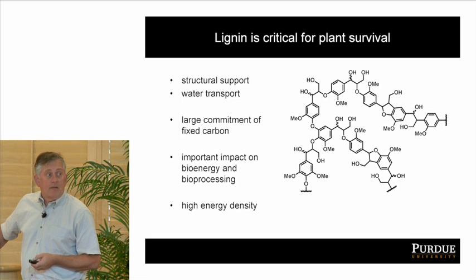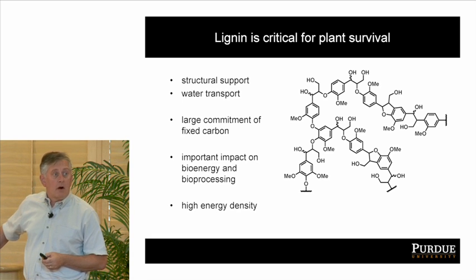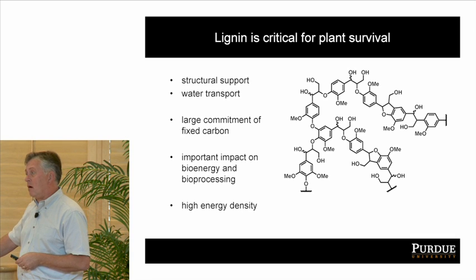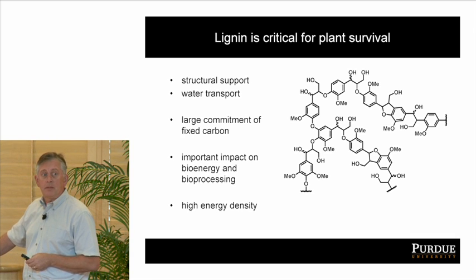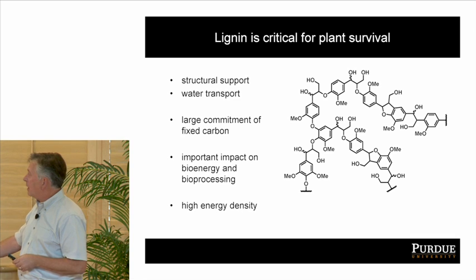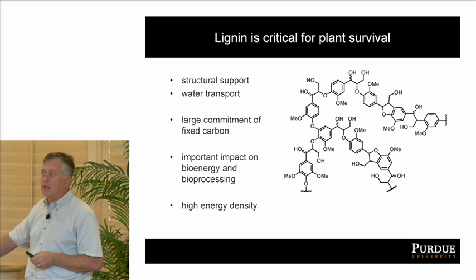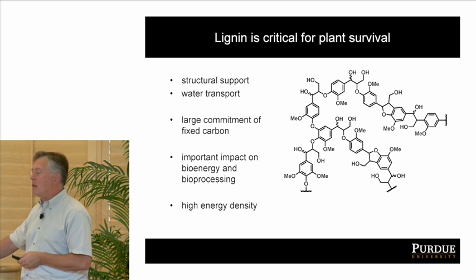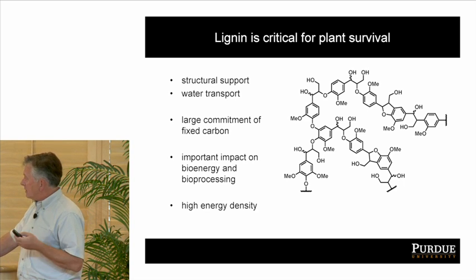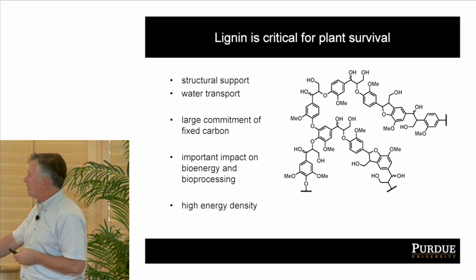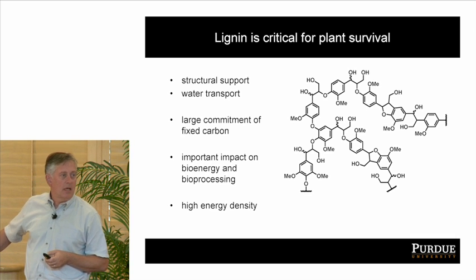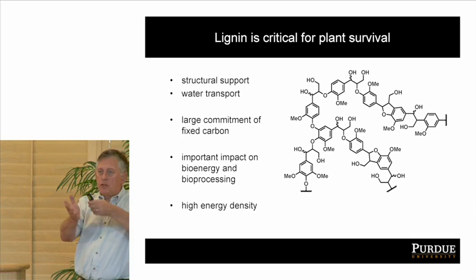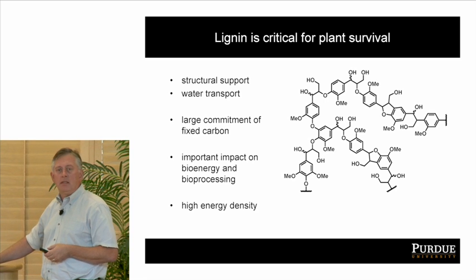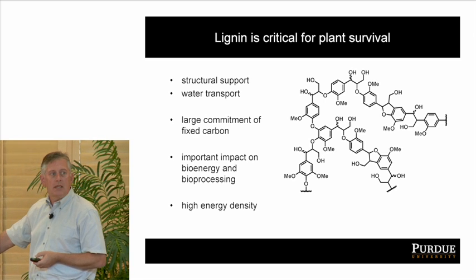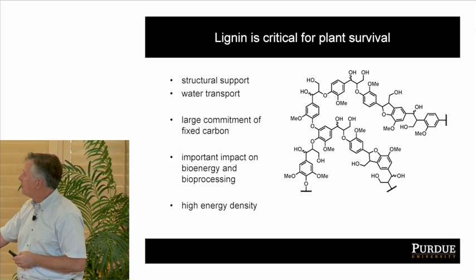With regard to plants, it's a very large commitment of fixed carbon, so it's probably not a big surprise that there are extensive regulatory mechanisms in place that make sure that the plant makes enough and not too much lignin. Perhaps something in the order of 20 to 25% of photosynthate goes into this polymer in plants. As I've mentioned already, it has an important impact on bioenergy and bioprocessing because it is intimately interwoven in the plant cell wall with the cellulose and other polysaccharides that we would like to get access to for biofuel production.